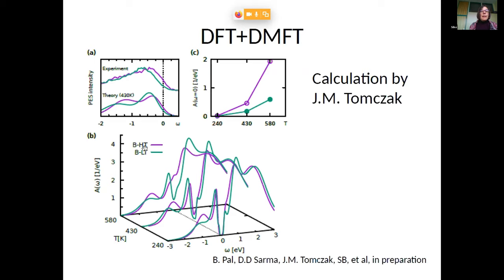So we take the high temperature crystal structure here in violet and the low temperature crystal structure in green, and we do calculations at high, intermediate, and low temperature. At high temperature, indeed, you have in the low temperature structure this kind of dip, and a nice spectral weight at the Fermi level. But when you cool down, there's a little surprise, namely both of these structures eventually display a gap. So that means that the high temperature phase, which seemingly is a metallic phase in the metal insulator transition scenario, is emerging from an underlying hypothetical zero temperature structure, which is an insulating material.